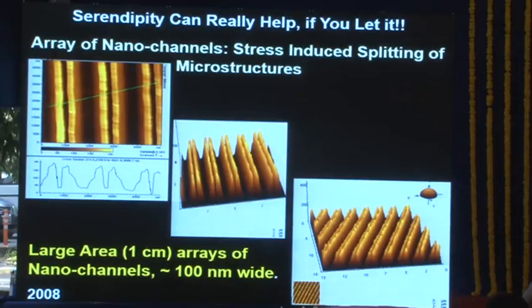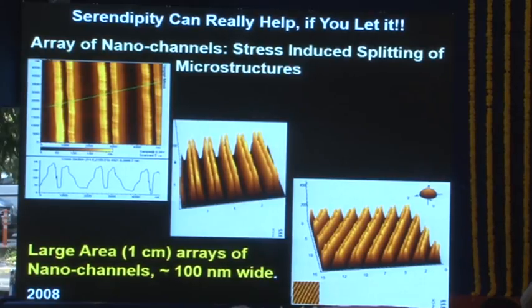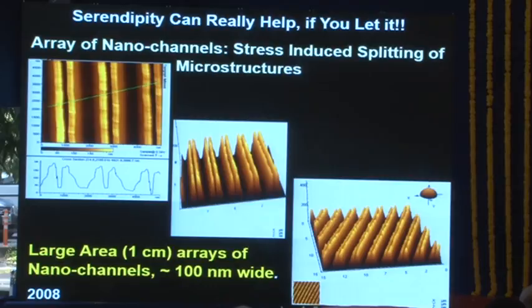So you see that the pyramids have split into two, starting from the top, and it has created a channel in between. So this is what he meant by failed experiment, because we wanted to make triangular structures, but after a while, it spontaneously transforms into this structure, which is undesirable from a student's perspective, because that was not the goal that he had set up for himself. But then, when you look at this structure, he said, look, this structure, in fact, is more interesting than the one that you wanted to make, because these are nano channels. You can make millions of nano channels in parallel by this self-assembly or self-organization.